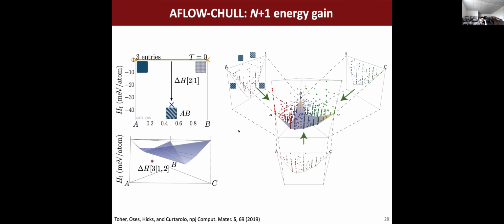So the idea here is pretty simple. If we're looking at a ternary convex hull, we need to remember that the ternary convex hull is in part made by the 3 binary convex hulls, okay? And if the binary convex hull has a really deep well, one of them or all of them, that's going to create more competition for the ternaries, which now have to compete with these really stable binaries.